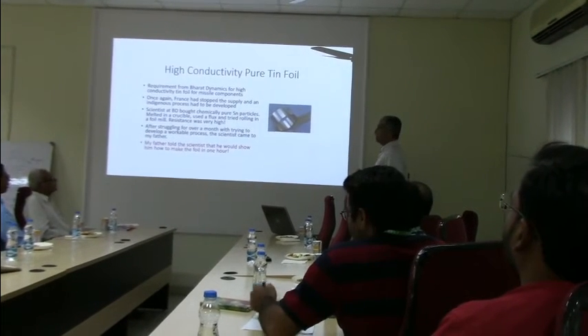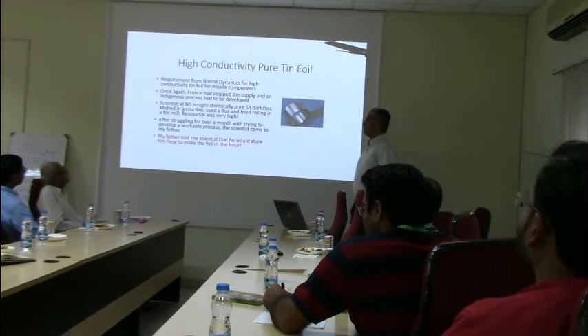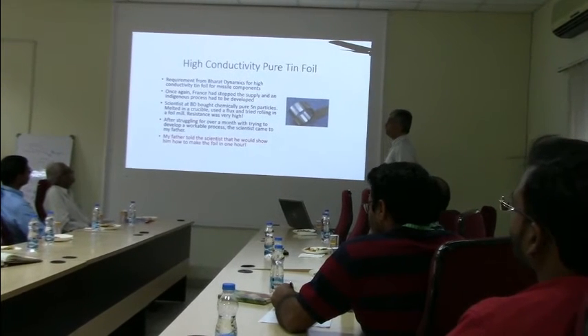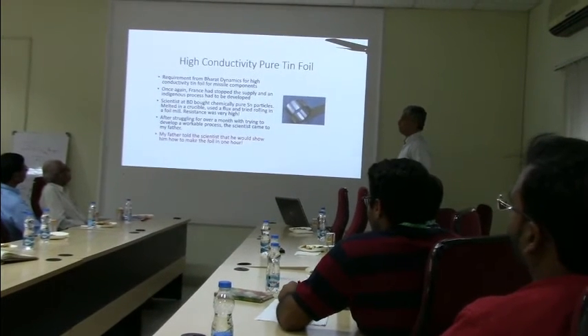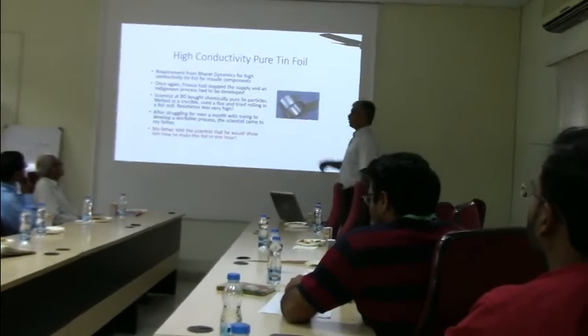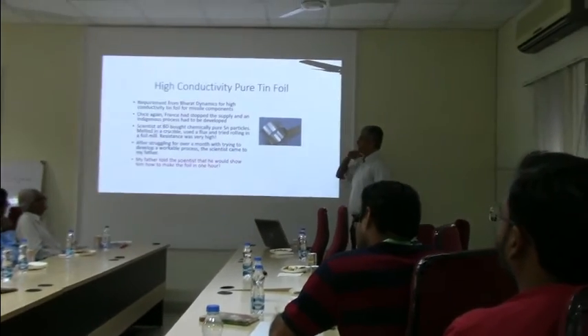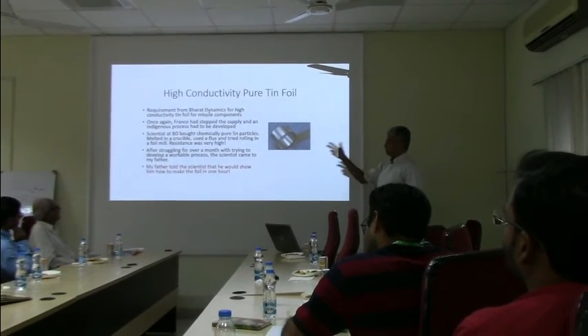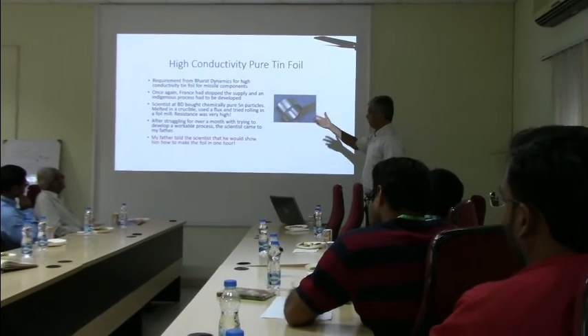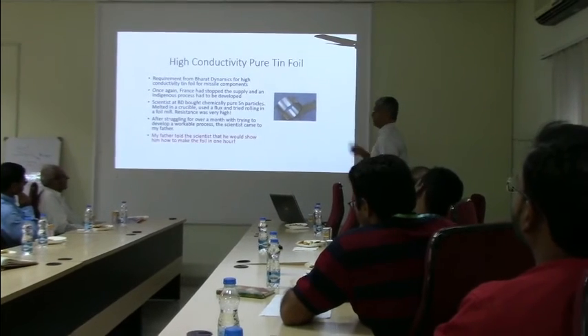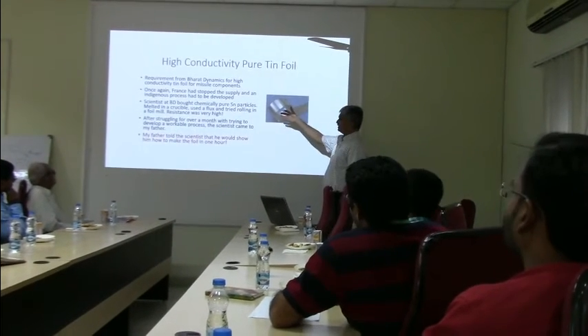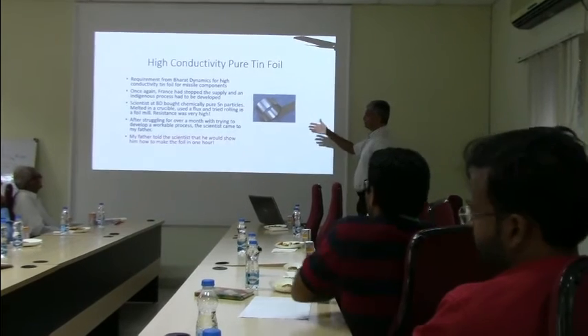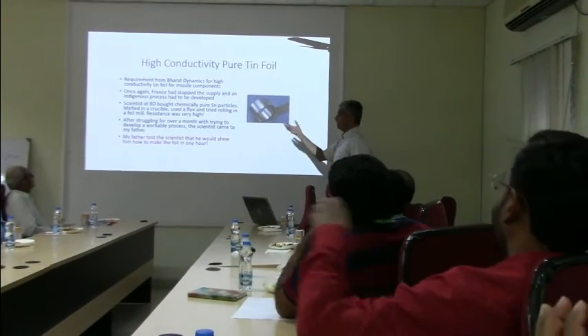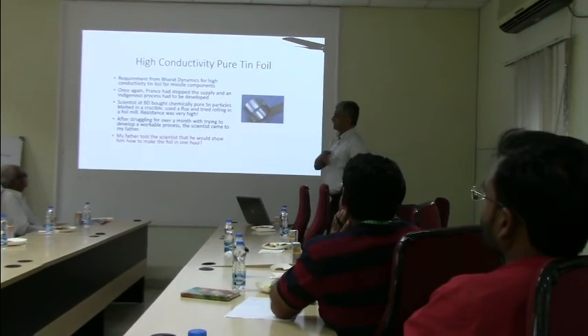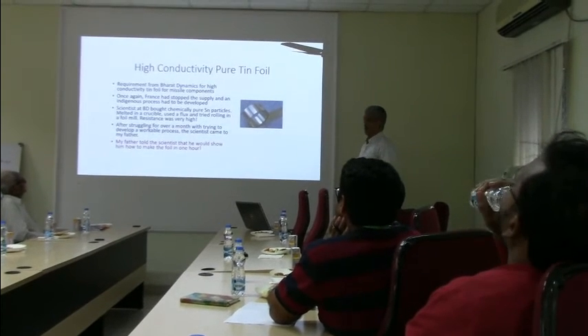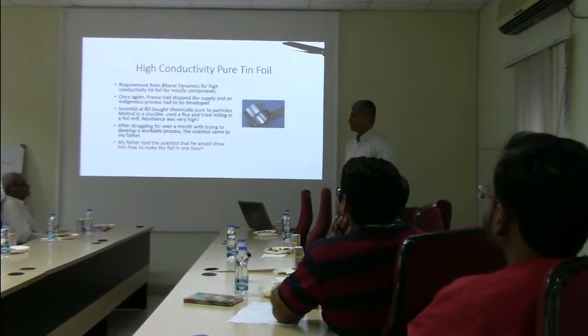Another project was on producing high conductivity pure tin foil. And this requirement came from Bharat Dynamics for a high conductivity tin foil for missile components. Again, France had stopped the supply, so we had to come up with an indigenous process. And so the scientists at BDL, good metallurgists, did the conventional thing, which is to get pure tin particles, melt it in a crucible, use a flux, and then roll it in a foil mill and so on. But the problem was that the resistance of this foil was very high.